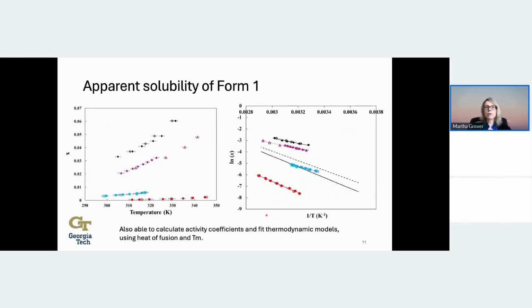So with the data from the Crystal 16, we were able to extract the solubility and corresponding temperature and concentration. And for the thermodynamic modeling, it's more natural to use the mole fraction. And so we plotted here the mole fraction for our measured solubility as a function of temperature. And we did that for all 4 solvents. I just realized the four solvents are not actually labeled here on these slides. But the red here is the acetonitrile, and the blue is the acetone, and then the alcohols have a much higher solubility.